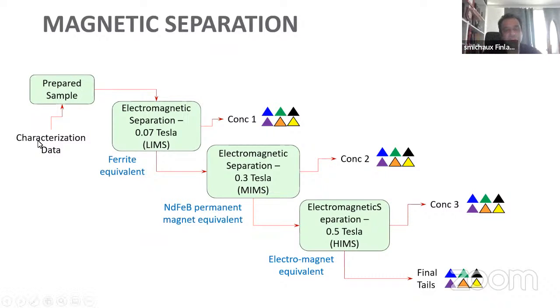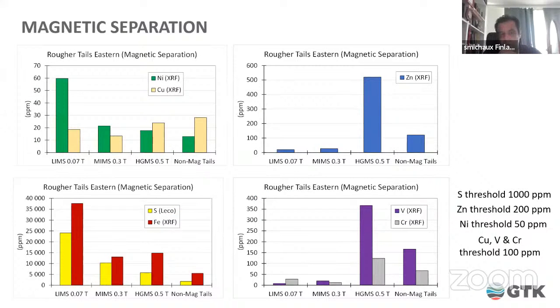So the idea was to take the sample, it's been characterized, feed it through the unit first at a low intensity magnetic separation, the equivalent of a ferrite equivalent, take the actual tailings out of that, run it through at a slightly higher level for medium intensity magnetic separation, and then take the tailings out of that and put it through at high intensity separation. And we'll look at the concentrates for all of that, and we can reconcile everything to the final tails. So here's the data. And so nickel and copper.